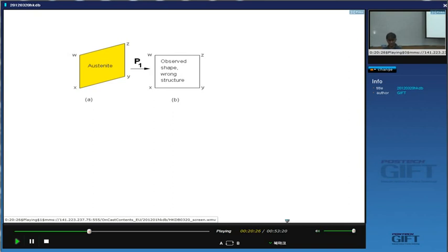We've proved that the combination of Bain strain and rigid body rotation is an invariant line strain. Okay? You cannot actually leave a plane fully coherent. So although we have the correct shape here, this is what we observe, it's the wrong crystal structure. So there's something missing here. Okay? And I'm representing this shape deformation by this matrix P.